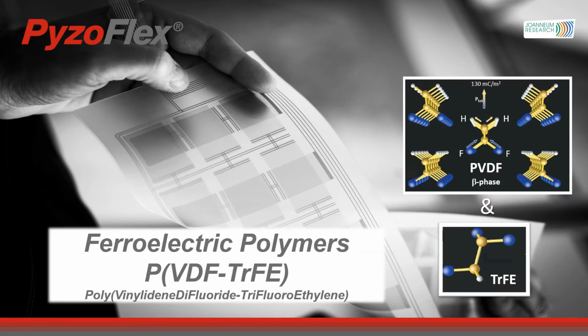Ferroelectric polymers are ideal candidates for such a versatile multi-parameter sensor technology. Pyzoflex is based on these materials, namely on PVDF-TrFE, a fluorocopolymer that crystallizes directly from solution in a ferroelectric phase. And this phase shows a high spontaneous polarization in the range of 100 millicoulomb per square meter.